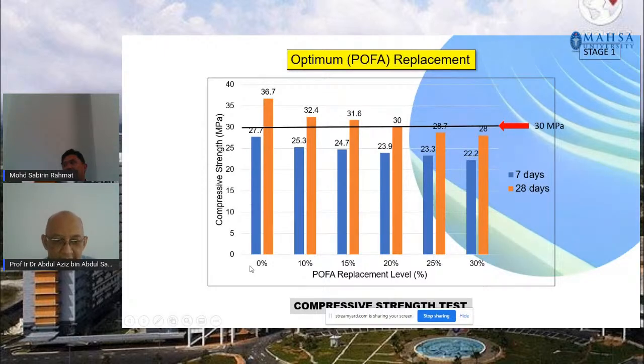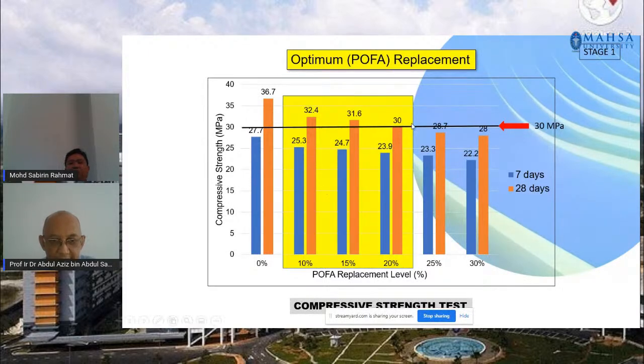So from the results, as you can see, POFA between 10% to 20% shows readings of 30, 31.6, and 32.4 megapascal. So with these 3 replacement percentages, it shows a reasonably good result of concrete strength in compression. As you can see there, the arrow shows the target strength, which is 30 megapascal. So this is palm oil fuel ash as a replacement for cement, and between 10% and 20% of palm oil fuel ash shows a reasonably good result.